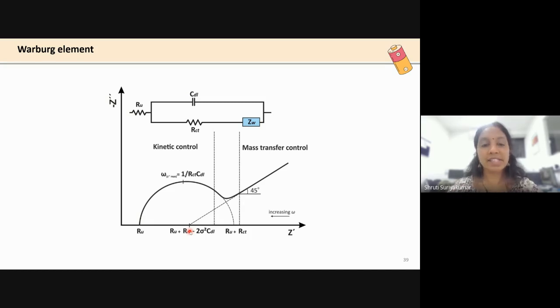So this is what it is going to look like. When you have assembled a cell with this kind of an equivalent circuit, which is a double layer, say for example, I'm assembling a cell and you're assembling a cell. My Ru is close to 5 ohms and your Ru is close to 0.1 milliohm. Obviously, we could say that yours is a better material, your electrolyte is better, and that's giving better conductivity, and therefore you can judge what's happening.